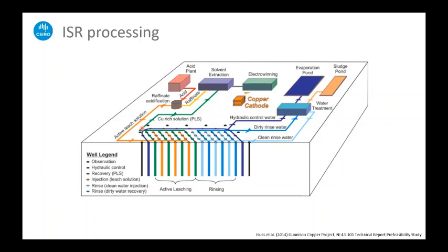There are also usually monitoring boreholes that are placed around the mine, and that's to monitor and check whether any fluid is moving out of regions of interest. And the PLS at the surface goes to solvent extraction and electrowinning for the generation of copper cathode. So that happens during the active leaching phase, and then that's followed by a rinsing phase, which is essentially the phase during which the deposit is flushed out. Now, because sometimes external water, groundwater, is drawn in to form this cone of depression, the drawing in of the solution to the extraction boreholes to prevent the movement outside the region of interest, there is additional water treatment that may be required.